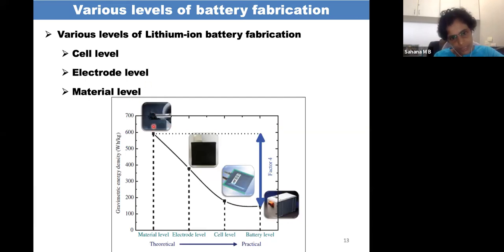But then when you make the electrode from these powders, you're adding many inactive materials. From material to electrode, you're adding a current collector, which is around 20 micrometer thick. It's a metal, either aluminum or copper. So it is an inactive material, and it adds up the inactive weight. And then we are also adding carbon black, which doesn't participate in the electrochemical reaction. So again, we are increasing the inactive weight. Then there is the PVDF. That is why the gravimetric energy density reduces from 600 to 400 watt hour per kg. From an electrode to the cell level, we are adding some more